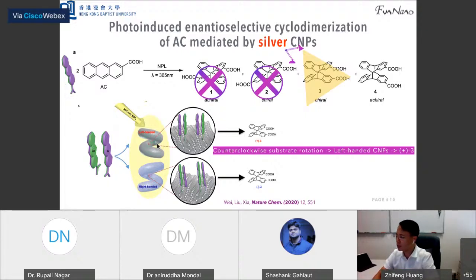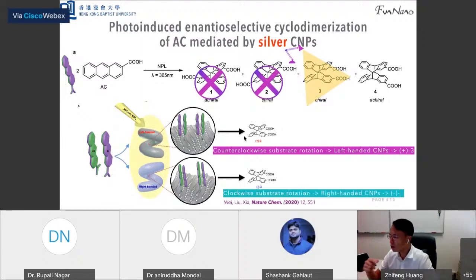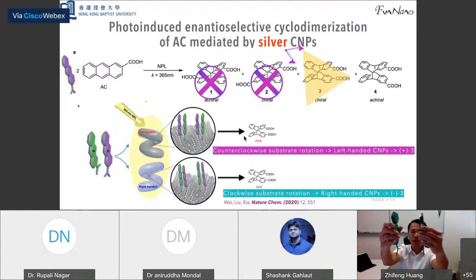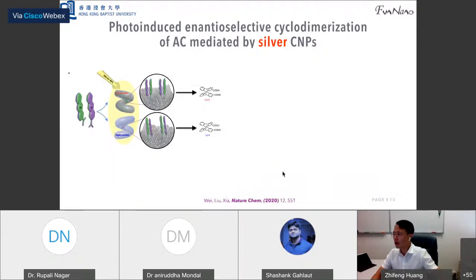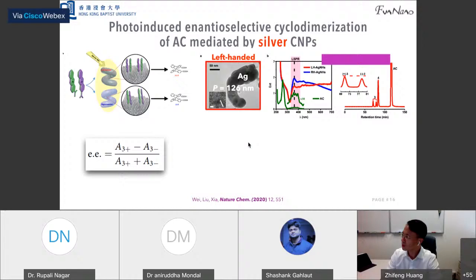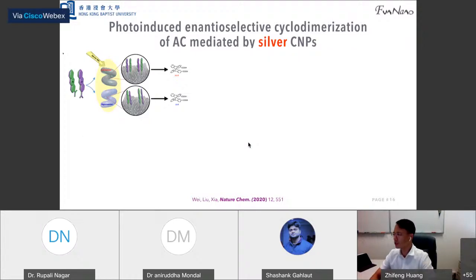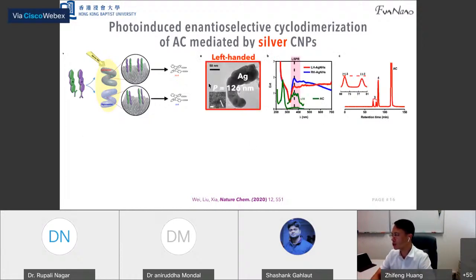So they're gonna generate the +3 chiral molecules preferentially. So if you rotate the substrate clockwise, we're gonna generate the right-handed nanohelical structures, and on the surface, the molecules prefer to have this green-green stacking. So they're gonna generate these -3 chiral molecules. So this is the conclusion, and I show you the result, right? So this is the left-handed silver,